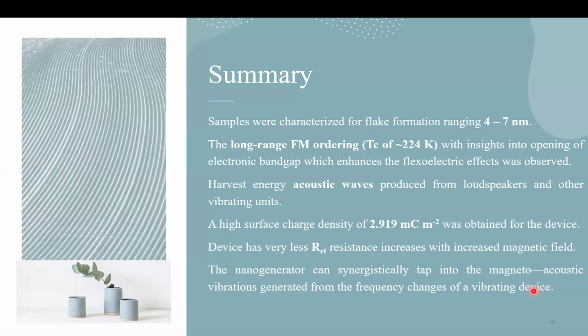So to summarize, the application of these 2D tellurides is that we are finding new materials for application in the device range. So all these devices are influenced by external magnetic fields. And if we can use this external magnetic field as an advantage for increasing the performance of the device, we can use these ferromagnets with higher Curie temperature, and we can harvest acoustic waves which are produced, and the devices are able to obtain a very high surface charge density of 2.9 millicoulomb per meter square for a very small device. And we can tap into the magneto-acoustic vibrations that are usually produced by these frequency changes in the vibrating device.